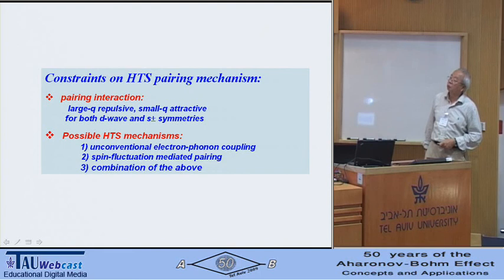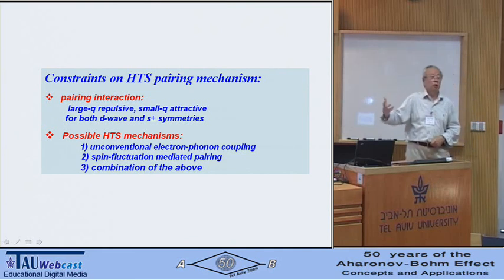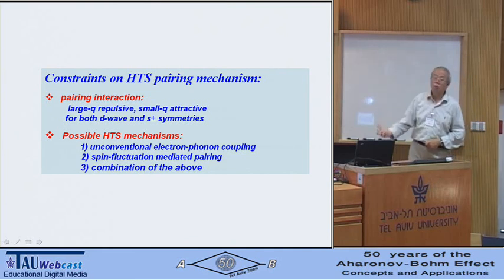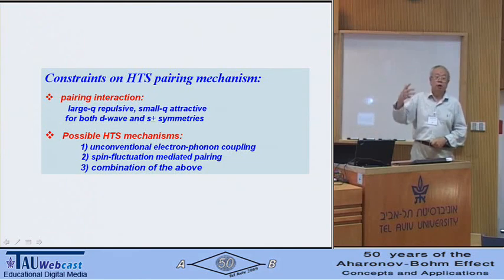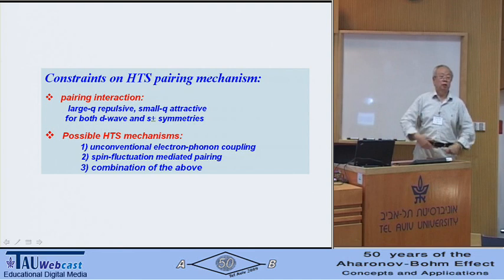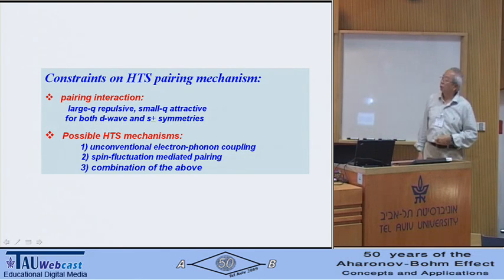Now, what are the possible high temperature superconductivity mechanisms? I would say if it's an electron phonon, it has to be unconventional. Why? Because some theoretical calculations indicate that a regular electron phonon coupling just simply does not support high TC in this system. So if anything, it has to be a specialized phonon, anharmonic, nonlinear coupling, and so on. I did some work along these lines recently.